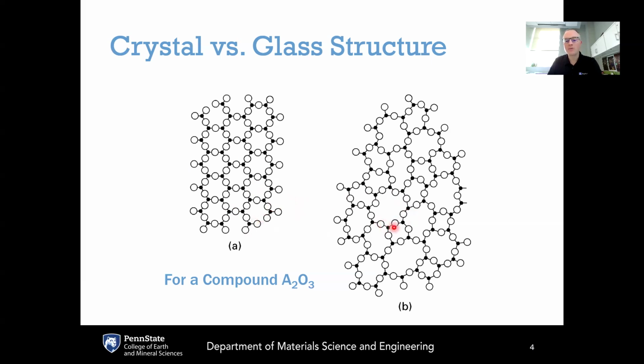However, if you go from the well-defined short-range order to the intermediate range order, the intermediate range order is less well-defined. There's still some sort of ordering, meaning that these triangular units are bonded to each other and they are forming ring structures, but there's more randomness in the size of the rings. So you can see here, this is a relatively small ring where there's only 4 triangular units making this 4-membered ring. On the other hand, this ring here has 1, 2, 3, 4, 5, 6. So this is a 6-membered ring, which is very similar to the 6-membered rings over on the left, but it looks like it's got a bit more variation of the bond angles.